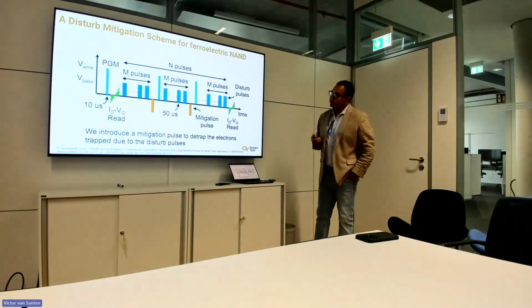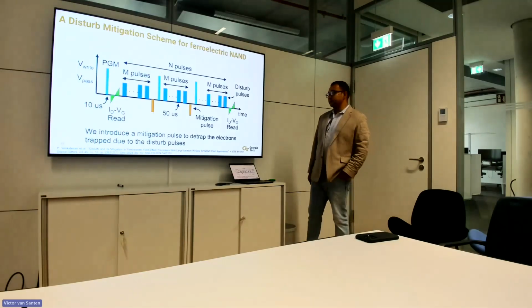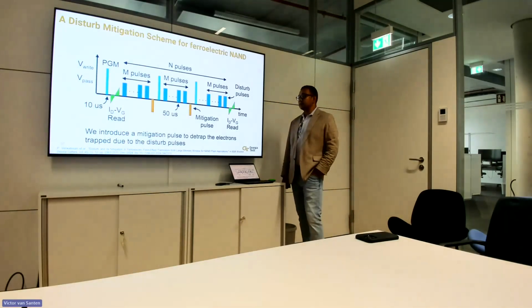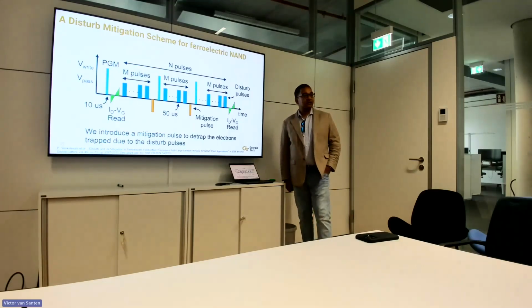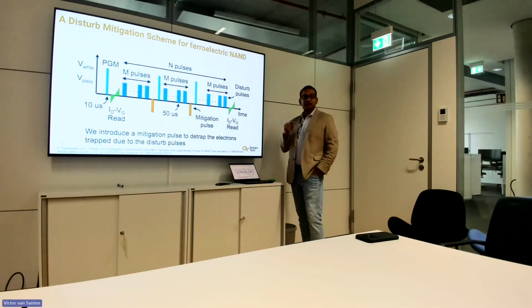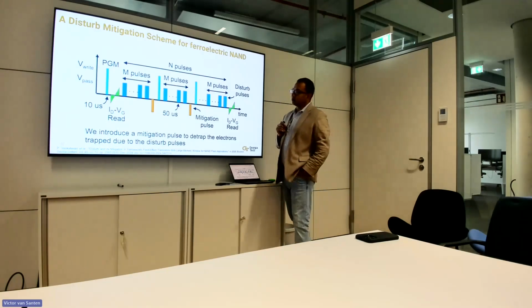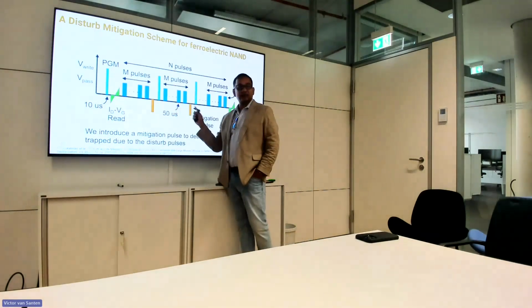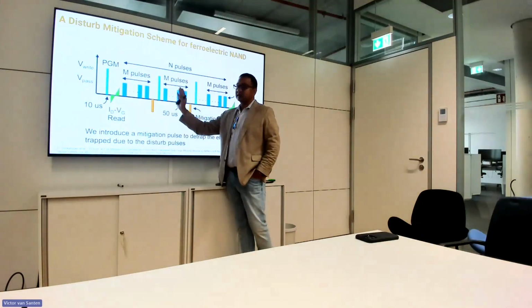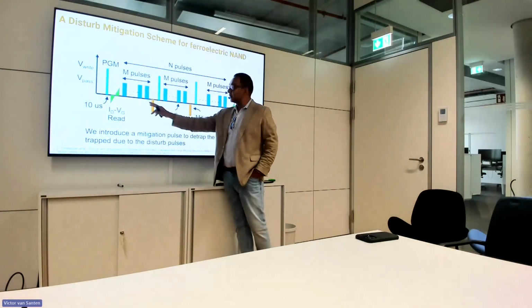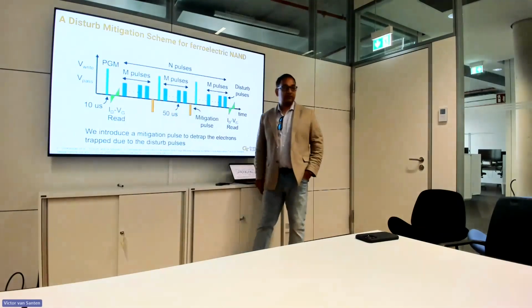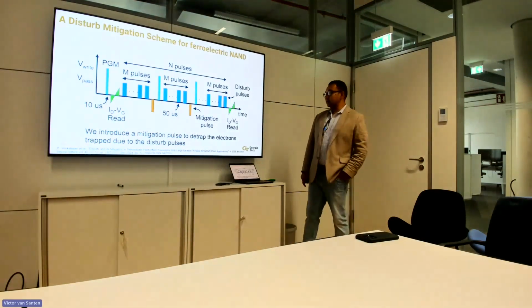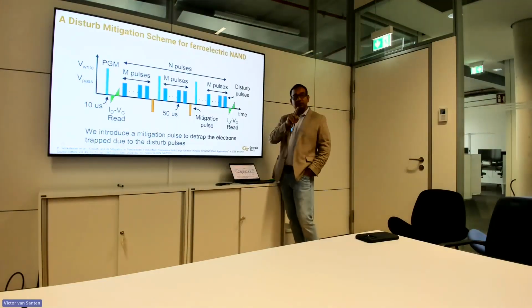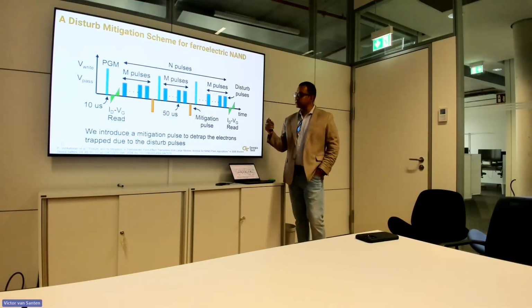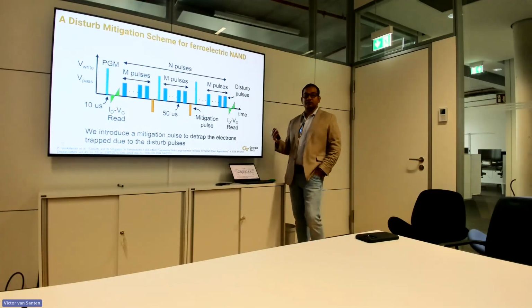Now, when we talk to our colleagues in the industry, this happens to some extent in standard NAND cells, especially when you have cycled them a couple of times. So in the NAND controller, there is a mitigation pulse technique, meaning that after a certain number of read pulses you have applied, you apply a mitigation pulse in the negative direction. What it does is that there are electrons that are trapped during these pulses, and if you apply a negative pulse, then all these electrons actually get flushed out. So it goes back to the original.